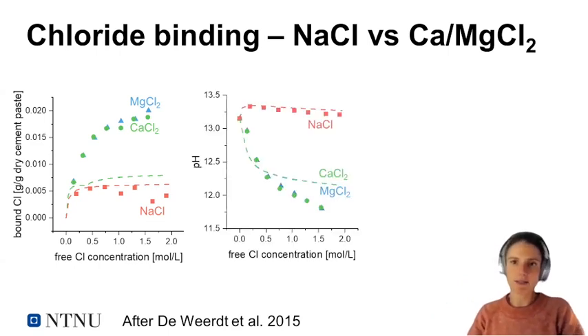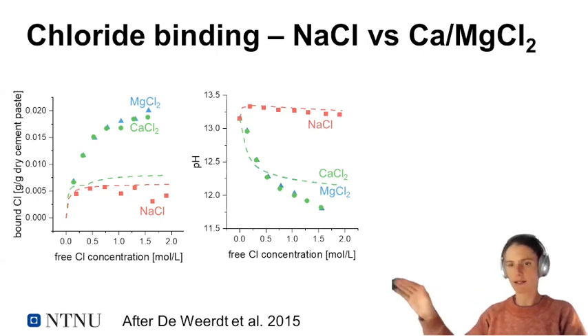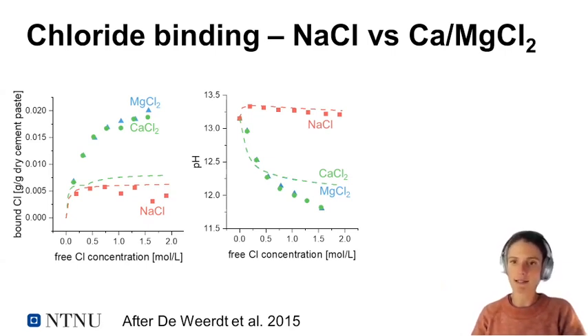We could actually link this to the changes in the pH in these solutions. So for sodium chloride, when we have a low concentration, we get a slight increase in our pH, and then it kind of levels out. Whereas for magnesium and calcium chloride, we have a considerable decrease in our pH when we're increasing the concentrations of these two salts.